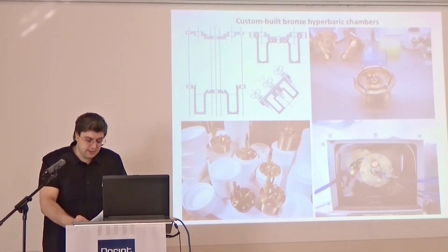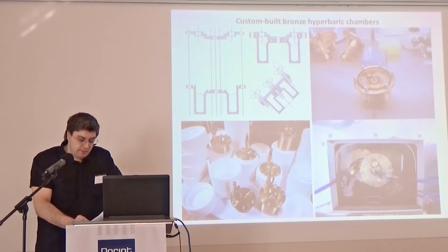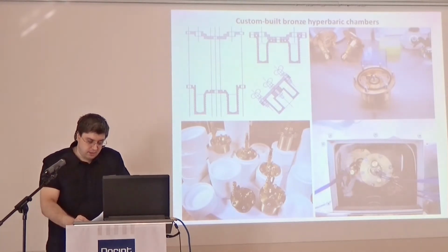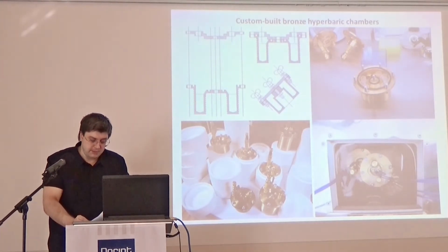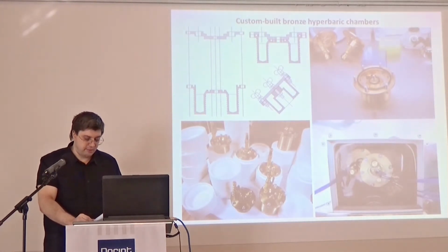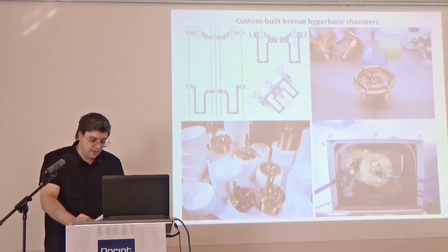Well, unexpectedly, 2.8 plus or minus 2.3% of the control cell group frozen by the above-mentioned primitive yeast protocol survived. And moreover, the fastest achievable cooling speed, by directly placing the pressurized hyperbaric chamber into liquid nitrogen, which we considered an absolute death sentence in the other control experiment, improved cell survival up to 22.5 plus or minus 13.4%.